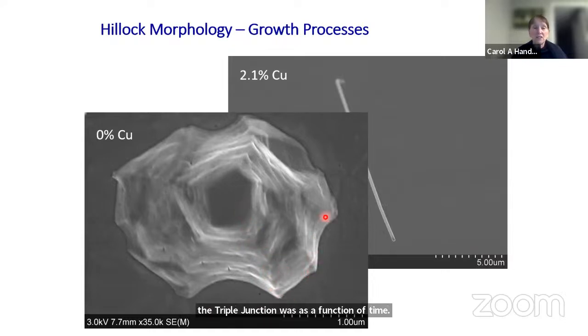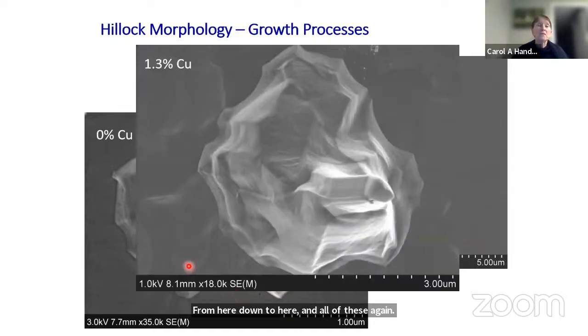And all of these, again, this is the curvature of the boundary on the free surface. And this is one in between. So you can see it grew up as a whisker over some amount of time. Again, this is the triple junction moving down.